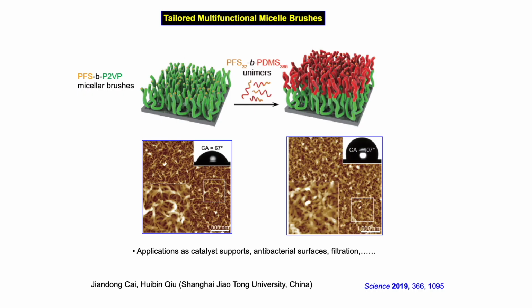So these brushes, you can do lots of interesting things with these structures. One thing you can do is control surface properties. If you have a corona-forming block that is hydrophilic, this gives you a hydrophilic surface. If you measure the contact angle, it's very low, about 67 degrees. But if you then grow another polymer from this that has a hydrophobic corona, this gives you a surface that is hydrophobic and the contact angle is much higher. So you can control surface properties.